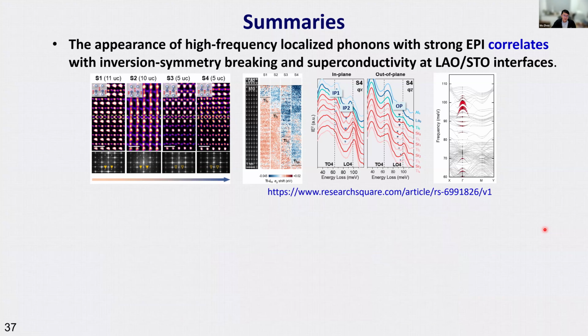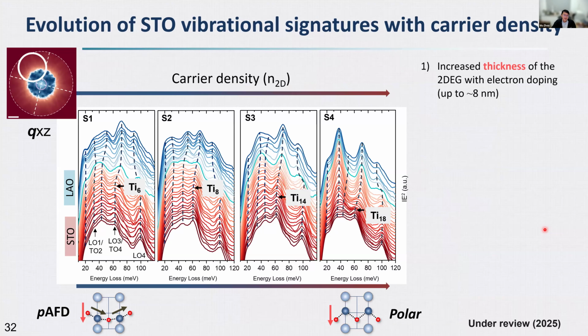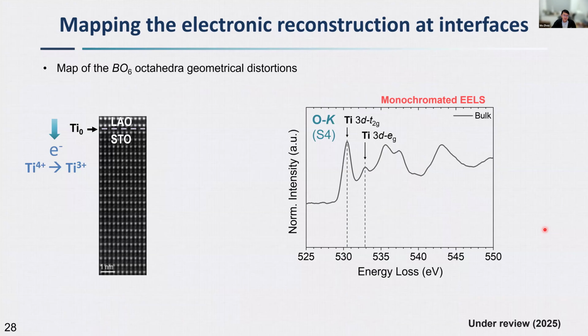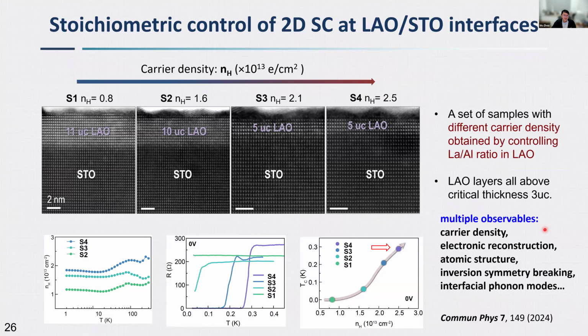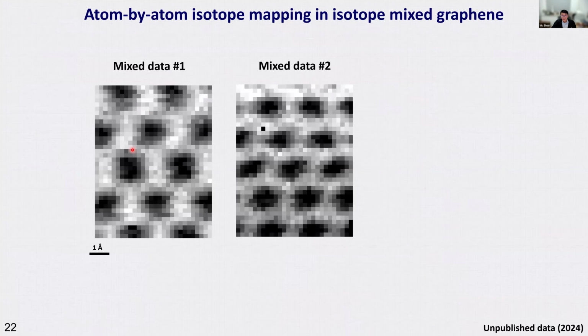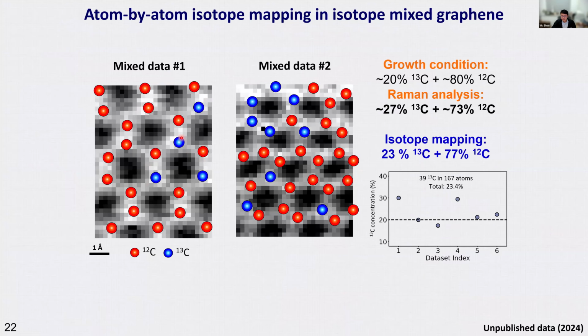Yes, let me go back. The image you see here is actually the simultaneously acquired ADF, and we extract the spectrum from individual atoms and analyze the peak position and assign it to each isotope. And then you can see it's not that homogeneous across different data sets, but the average is very consistent with Raman and the nominal growth condition.